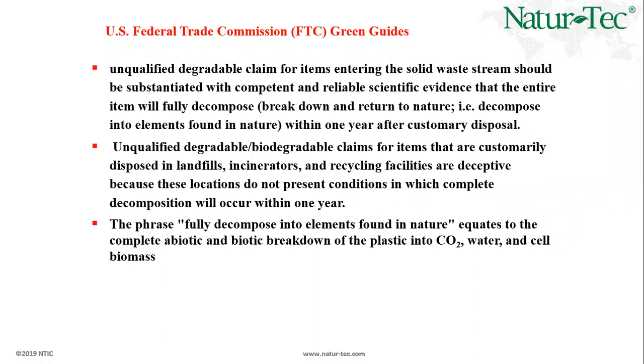Now, unqualified claims for items entering the solid waste stream should be substantiated with scientific evidence that the entire item will fully decompose. There are lots of reports in the market where people run the study for 15 days and say that 10% or 20% of my material is biodegraded, and so in the next 180 days 90% would be biodegraded. So they do an extrapolation, which is not correct. We cannot extrapolate a microbial assimilation mechanism because it's not a linear mechanism. The way microbes consume the carbon in the food source is a completely different mechanism. It cannot be plotted in a certain pattern. It cannot be a linear pattern or a parabolic pattern or an exponential pattern. That's one.